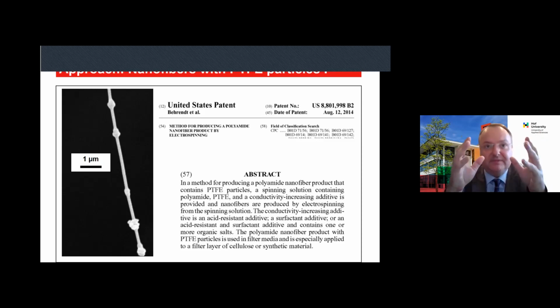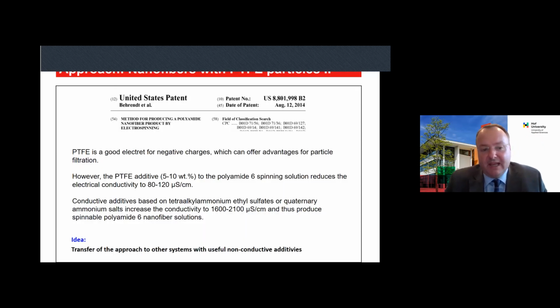If you consider this simple lab scale trial, you have an injection of charges into the droplet, and therefore you need at least a certain degree of electrical conductivity to ensure that you can inject the charges into the droplet. But if you have PTFE in a solution or in a dispersion, you will lower the electrical conductivity. And therefore, you have to increase the electrical conductivity of such a solution. I will give you some values. If you add PTFE particles in a range of 5 to 10% to a polyamide 6 spinning solution, you have an electrical conductivity of roughly 100 microsiemens per centimeter. And therefore, you have to increase this conductivity.